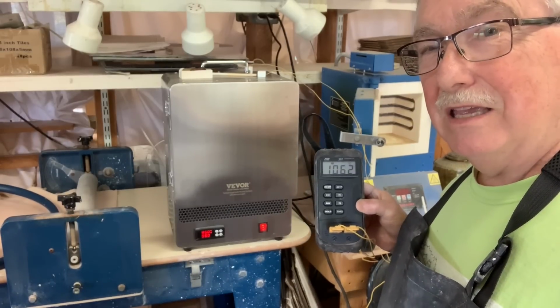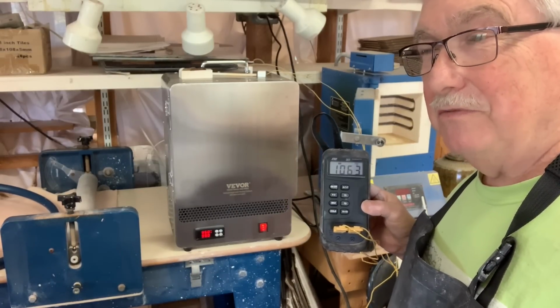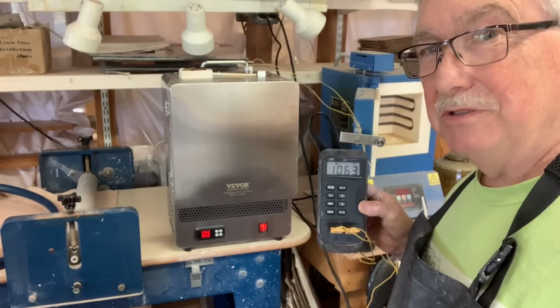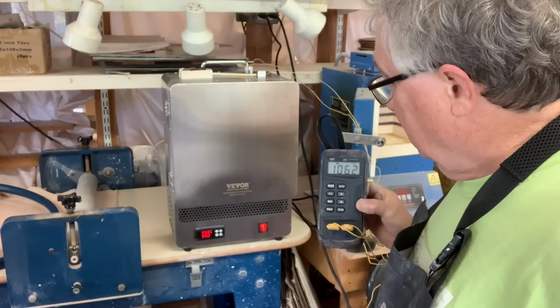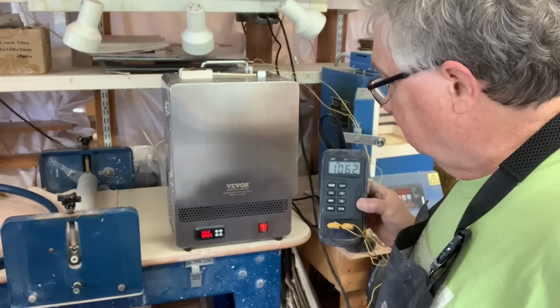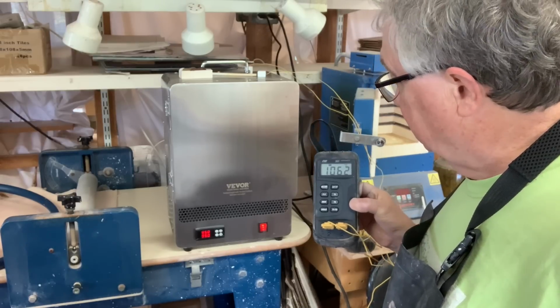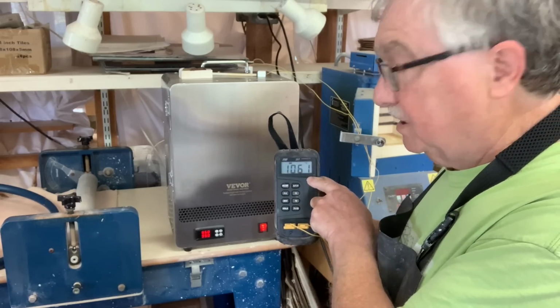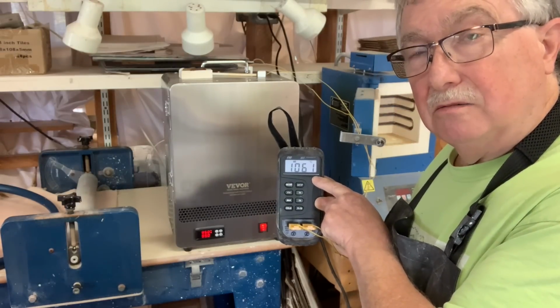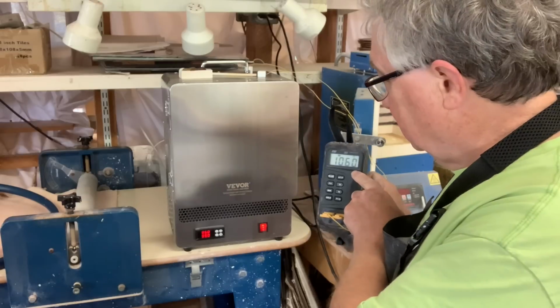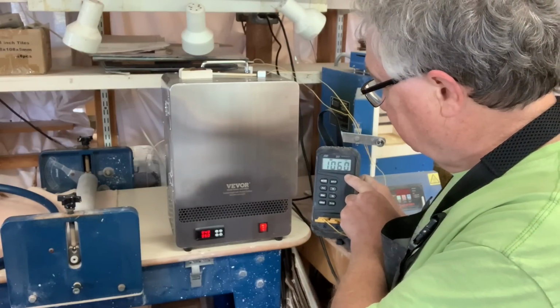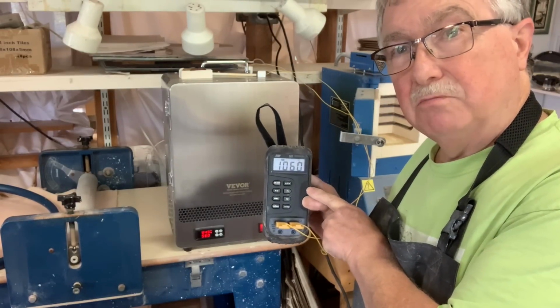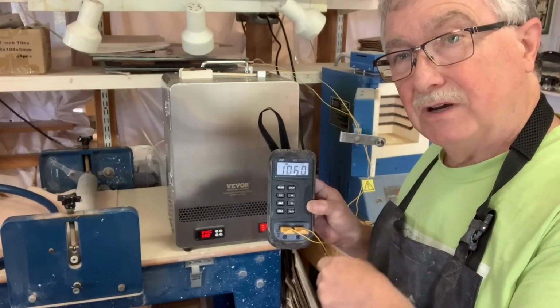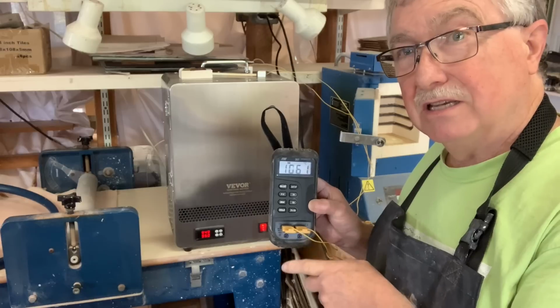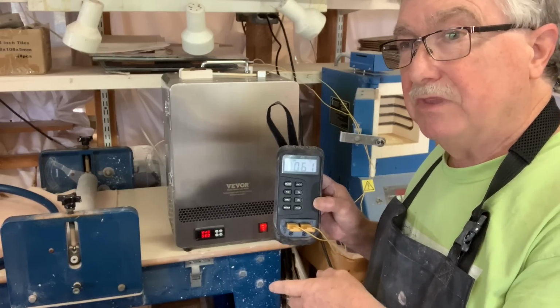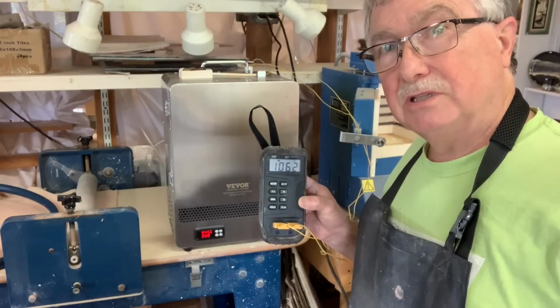Okay, it didn't take long at all, we're talking 35 minutes, max, to get to temperature for Bisque firing. And it's reading 950, that was my target, and it's actually on 950. This one is reading 1061. So we have a dispute of about 110 degrees. So that's the difference. So my feeling is this kiln is firing about 110 degrees hotter than the actual pyrometer in the actual kiln is telling you.